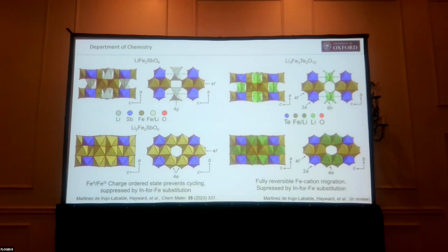But the problem with this material is that the tellurium redox couple is really close to the iron 2+/3+ couple. And we end up reducing tellurium to the element. So again, what we can do is replace some of the iron with indium. What that does is expand the iron octahedron by chemical pressure. And what you find then is that actually pushes the iron redox couple up, and you get away from the tellurium couple. But in these cases, this system is pretty hard. We can mitigate against the cation migration, but we do it at the expense of the electrochemical activity.